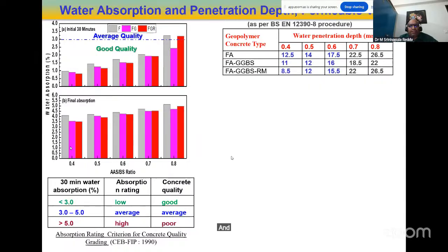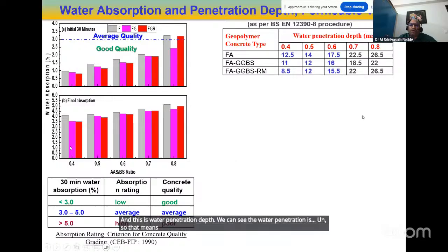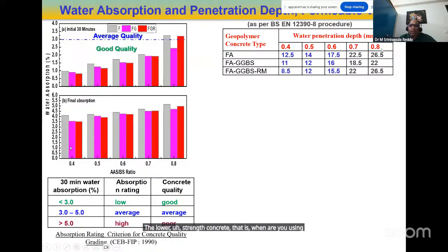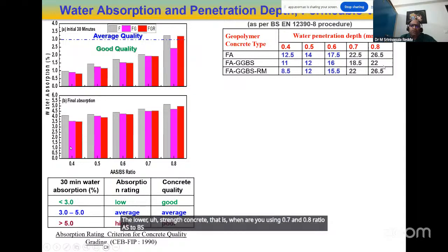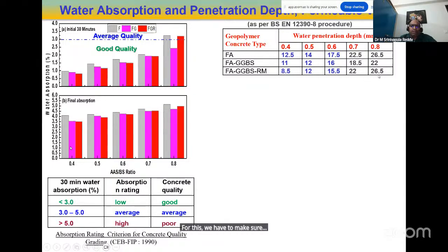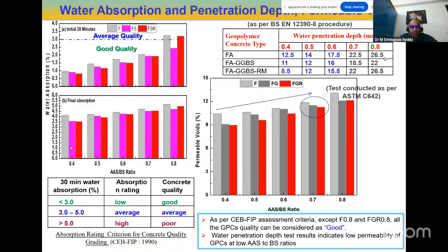And this is water penetration depth. We can see the water penetration is more, which means we need more cover when we are using the lower strength concrete, that is when we are using 0.7 and 0.8 AS to BS ratio concretes. We have to be careful while providing the clear cover, because the penetration is up to 26.5, so if you have 25 or 20 cover, that will affect the corrosion. Except for 0.8 fly ash, fly ash GGBS and Redmud 0.8, all are showing good quality.